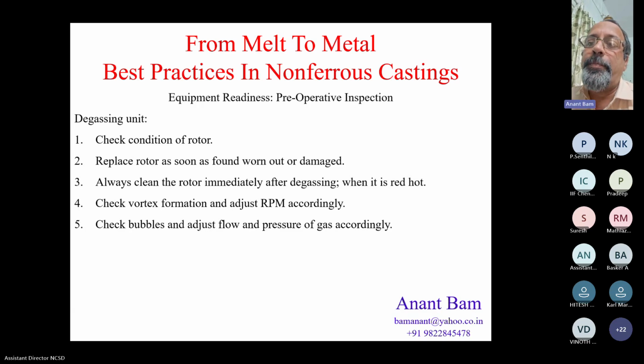Next is check the bubble adjustment. Check the bubbles and adjust the flow and pressure of the inert gas. The bubbles should not be visible. There should not be a burp or blup of a big bubble coming out. Aluminum metal should not splash out on the top of the furnace. And again, a thumb rule is that as per theory of bubble formation and effectiveness, the bubble size should be between 1.5 and 3 mm. But nobody can really measure that size inside molten metal.